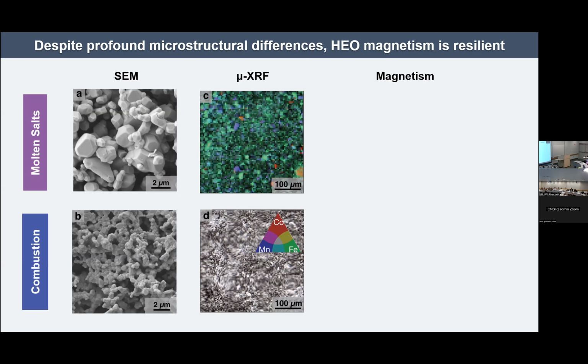Now, if we look at the combustion sample, what we see is actually something that looks like an SEM image because it's entirely gray and white, and that's because our 3 elements represented here are in roughly equal proportions everywhere. So this sample is extremely homogeneous.